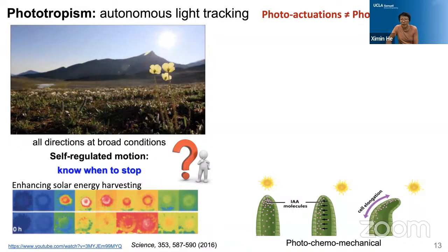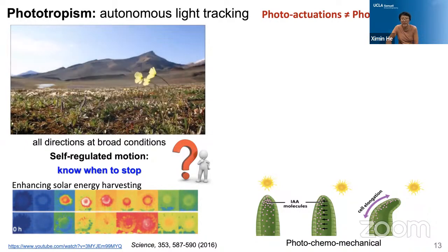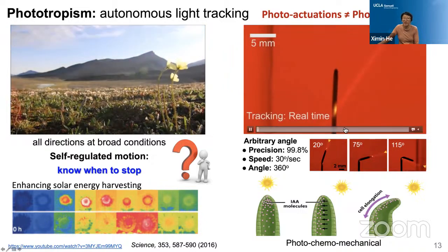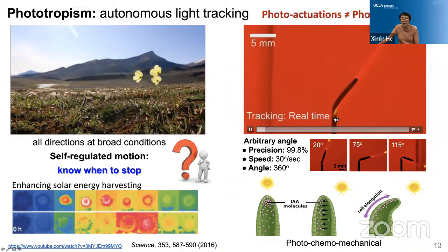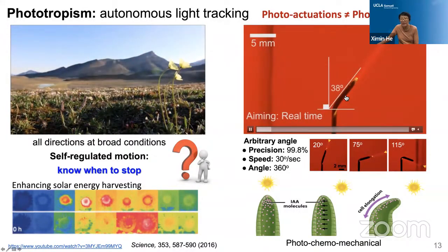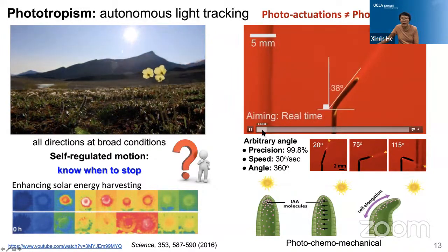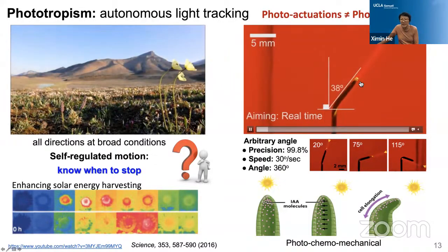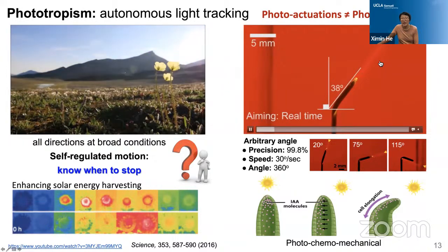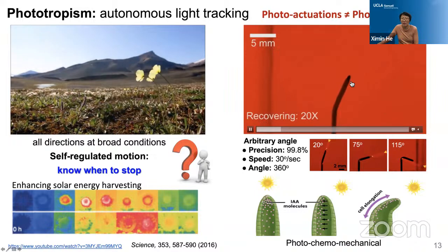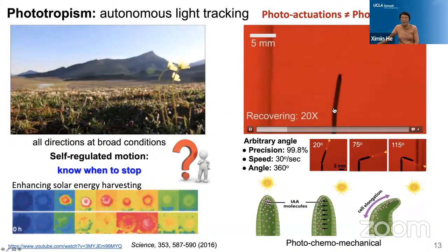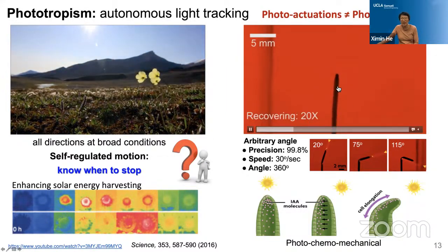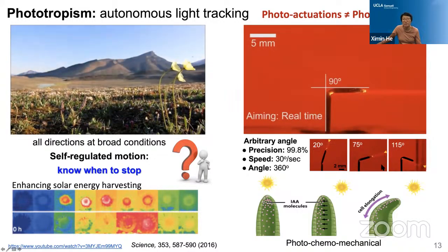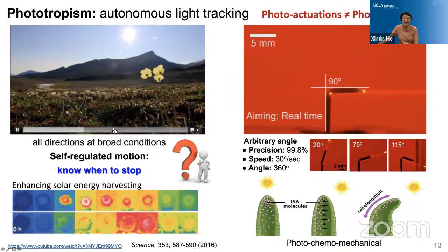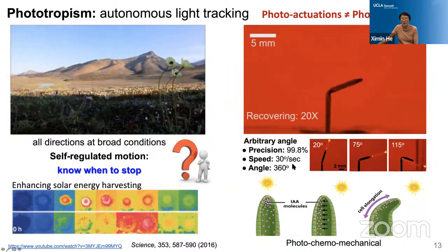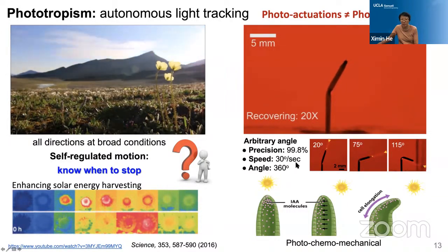So we were thinking if we can develop some mechanical responsive material, we may be able to achieve this. And then here, this video shows we make this photothermally responsive hydrogel pillar, and then we shine a light at an arbitrary angle, like 38 here in this case, and you can see the pillar just swiftly bend over to this angle, and then very steadily point to the light as long as the light is on. And then we turn off the light, you can see this pillar will immediately go back to the original upright position. And this pillar can track the light coming from almost all arbitrary angles across the entire 3D space. And this bending, like tracking speed, is much faster even than the natural plants, right? So it can take only about 3 seconds to track the 90 degree angle.